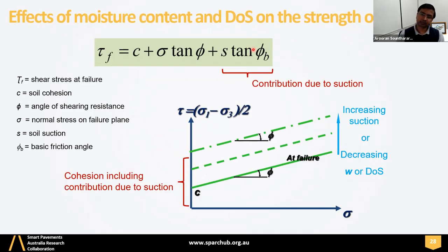So what happens is when the degree of saturation in the pavement changes, that means when you change the water content, right, this failure envelope also changes. That means there is a certain contribution due to suction, right? Degree of saturation can change in two ways. One is by changing the water content, and the other is by compacting it further. So when the degree of saturation changes, there is a contribution here, which is primarily apparent cohesion, and that shifts this failure envelope upwards.